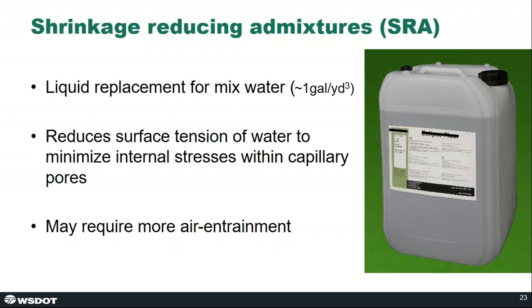And this product oftentimes may require more air entrainment, and high doses can destabilize the air void system. I mention that because it's important that even though we have certain performance criteria that we specify, they need to be compatible, because oftentimes the approach to meet one criteria can compromise the other. And so it's not simply a matter of picking out the dream durability properties for all the tests you want to subject it to. There actually has to be an economical solution there, and sometimes that can involve some compromise.